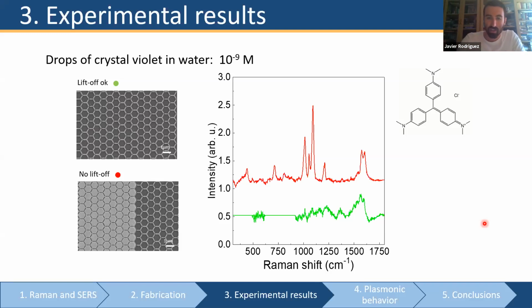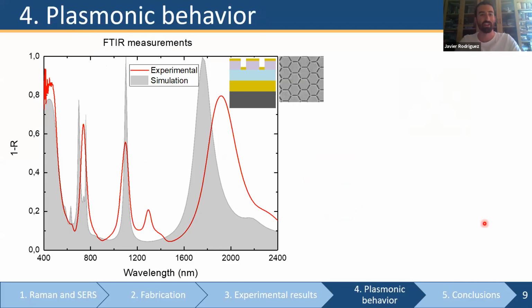So after seeing all these results, we were very curious and we wanted to go deeper in the reasons why these samples without the liftoff seem to systematically outperform their companions with the liftoff process performed successfully. So in order to gain further information on what was going on here, we took advantage of some additional optical measurements and numerical simulations performed on this last structure that I presented to you.